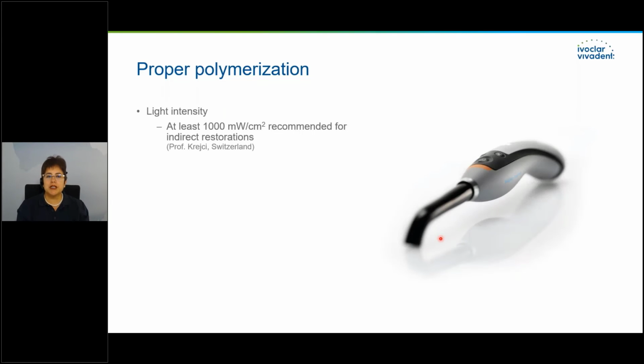So it is recommendable to use powerful light curing devices, because you saw that from the first millimeter, you will have a drop of 50 to 80% of the power intensity reaching the cement. Professor Krejci from the University of Geneva always recommended having at least a curing light of 1000 milliwatts per centimeter square. And now the following question will be about the exposure time.